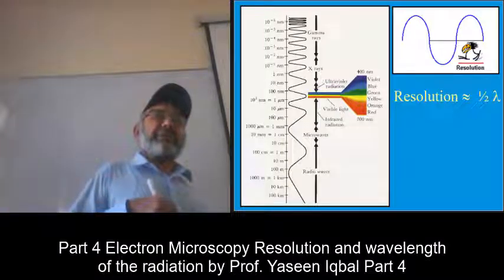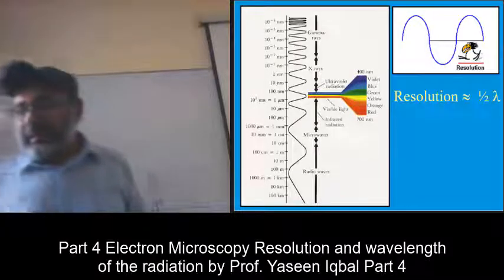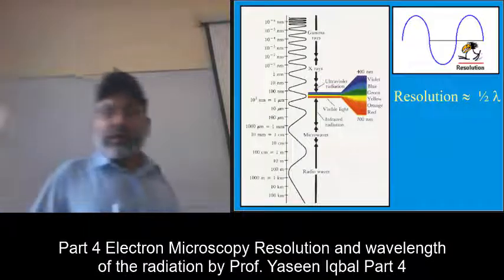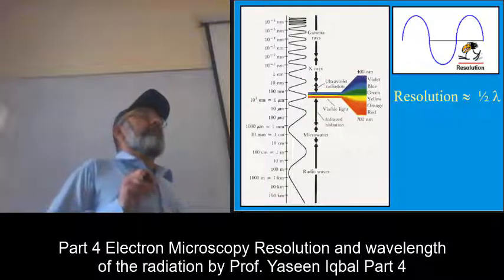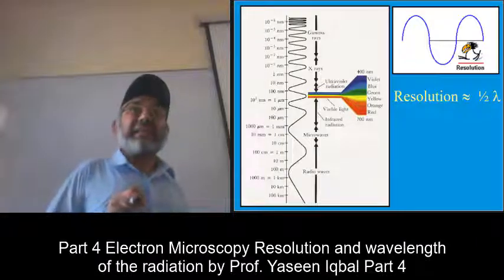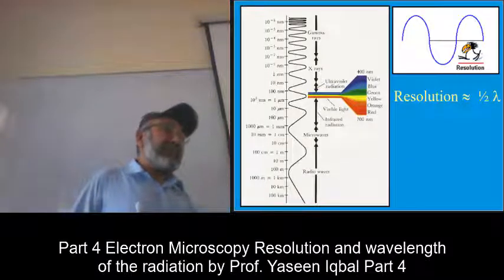Similarly, people usually say that with the Scherrer formula you can measure the grain size. It is not grain size. A grain may contain many crystals. It is the crystallite size, right? So never say grain size.